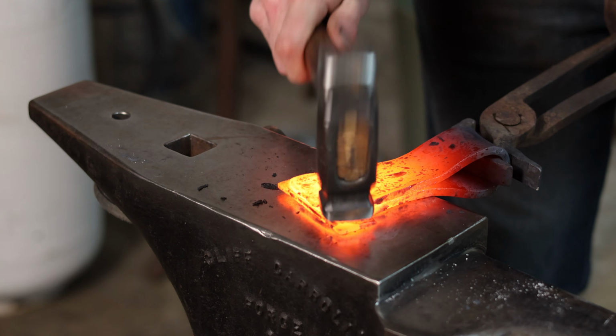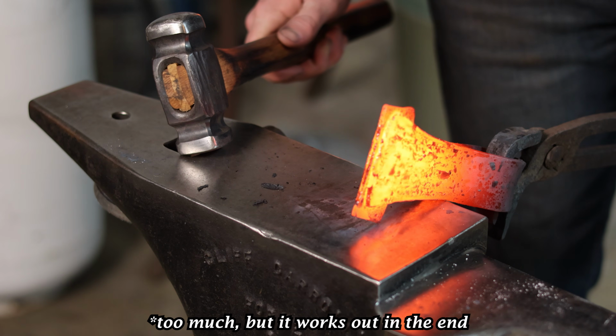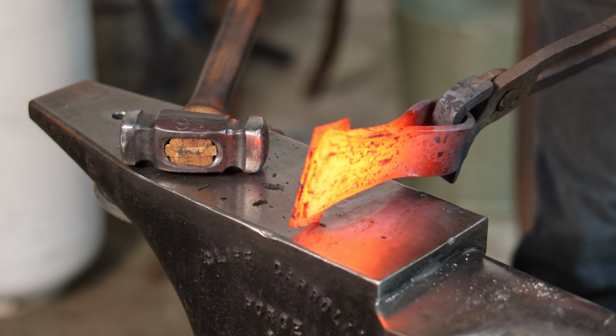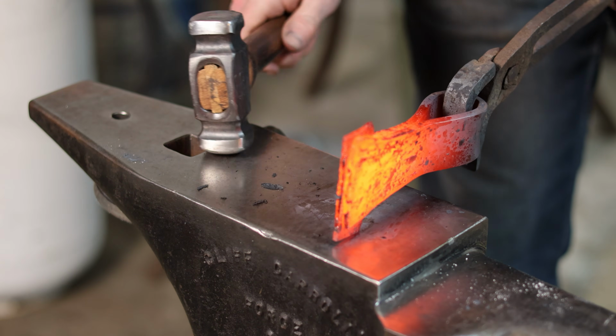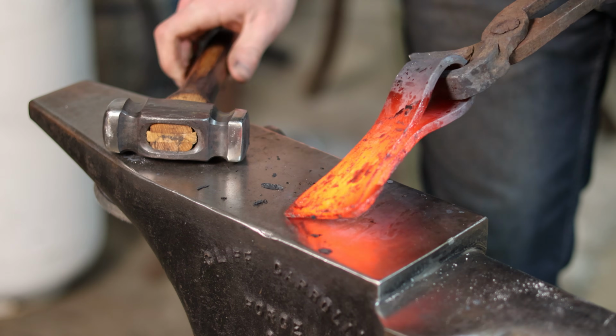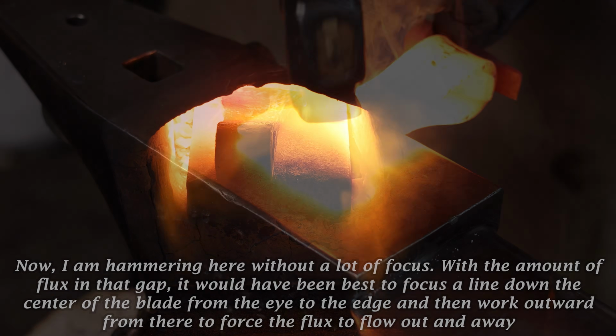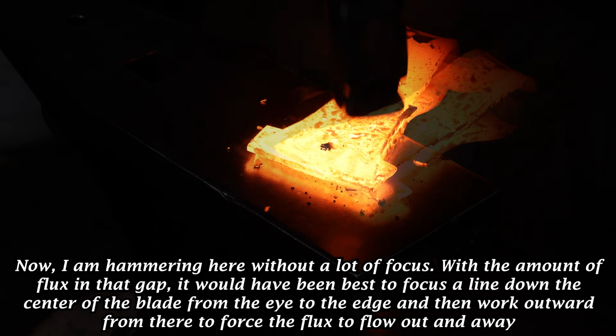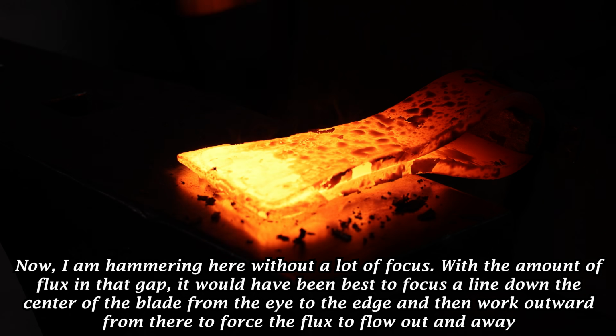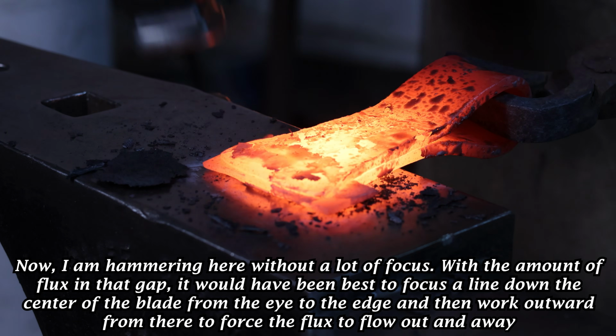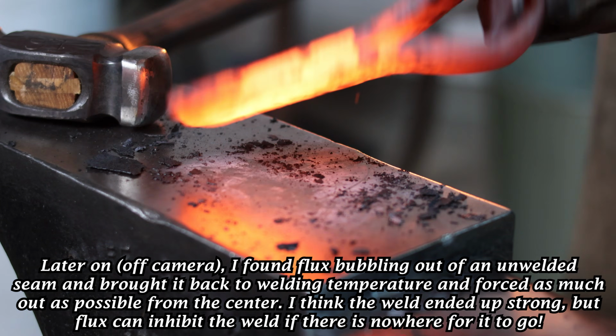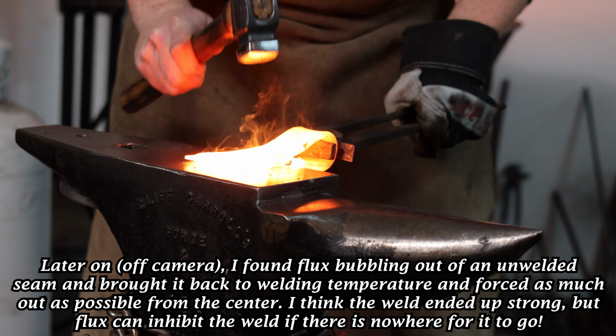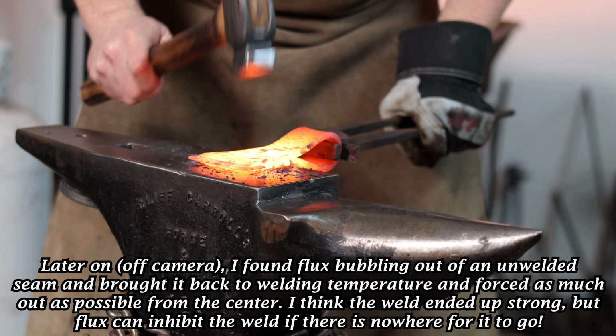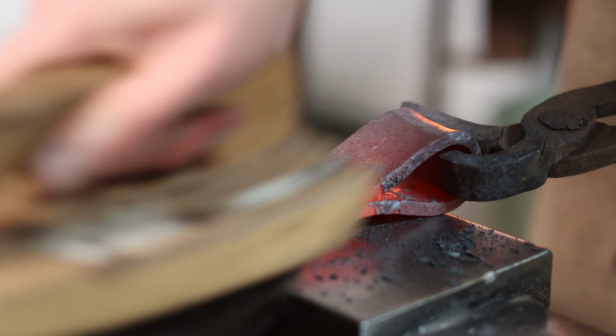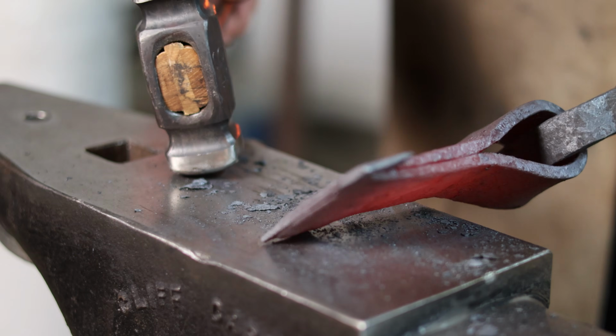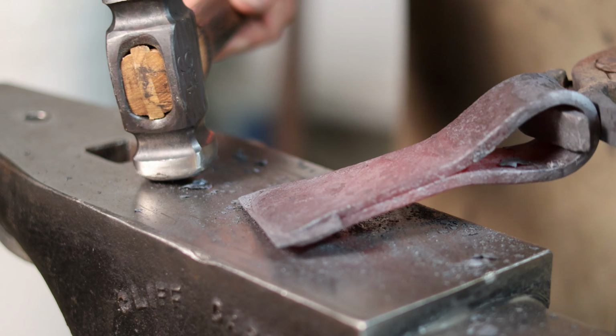And this has a pretty decent amount of flux in there to try to prevent any oxidation between the pieces of steel that would prevent any forge welding. And now I'm going to bring this up to a welding temperature, and we'll give it some nice light taps to hopefully get a really nice weld on this. After many heats at a welding temperature, that should be all pretty well welded together.